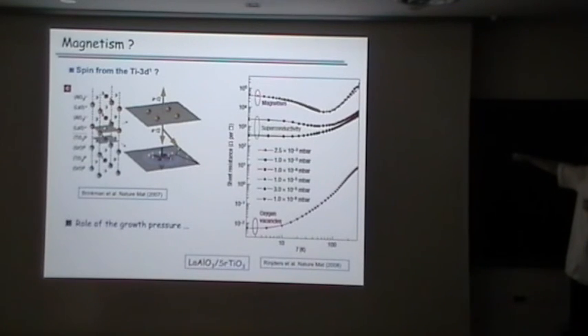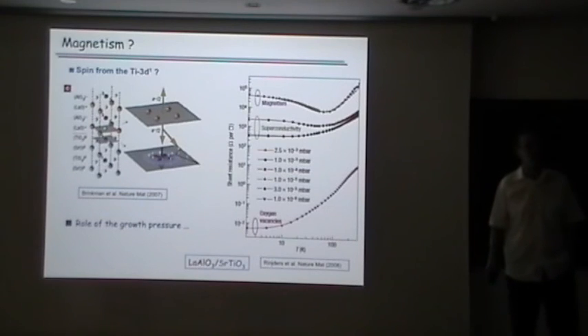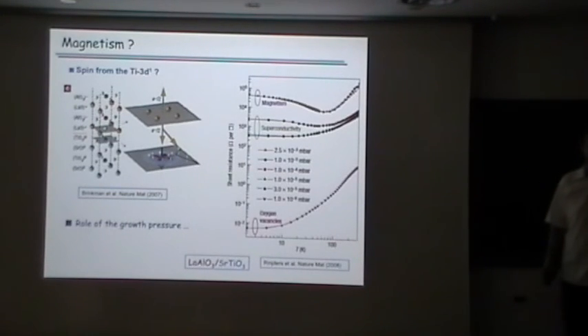And indeed, I don't remember the number of carriers here, but it's quite low still. But it's probably in the range of 10 to the 12 to 10 to the 13, or something like that here. Okay, which goes in favor of very low doping, but still it's rather high doping. I mean, the number of carriers is quite high. So how many per unit cell? Yeah. I mean, I think it's much less than 1%. Mm-hmm. And it's strange to empty out a D-band and to find magnetism on a large scale. Yeah, I put a question mark. No, I think it's a good question mark to have.